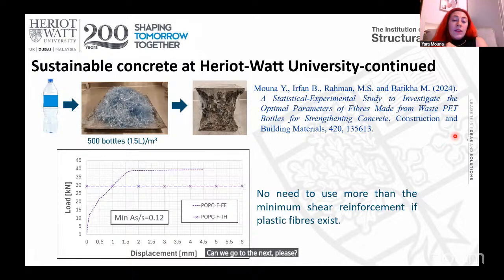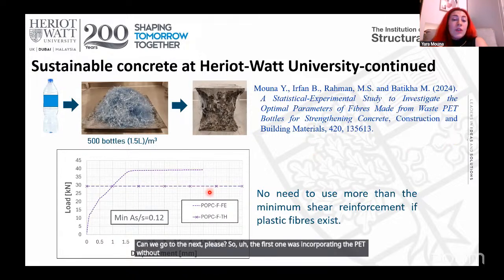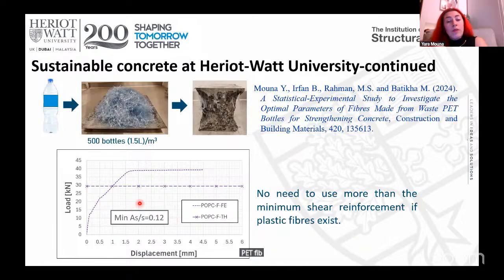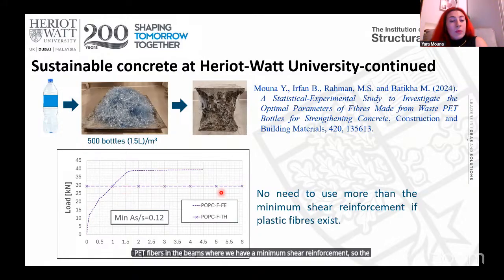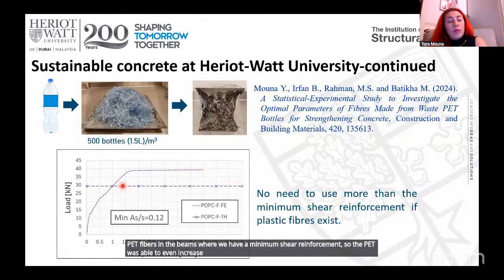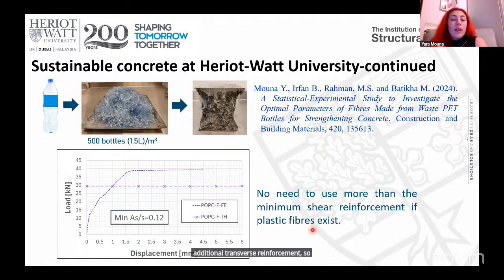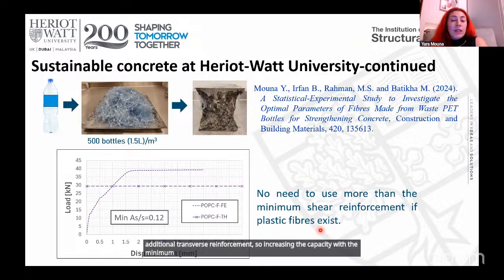So the first one was incorporating the PET without any shear transverse reinforcement. But even if we incorporate the PET fibers in beams where we have a minimum shear reinforcement, the PET was able to increase the capacity of these beams, more than without even adding any additional transverse reinforcement. So it increases the capacity with the minimum shear reinforcement.